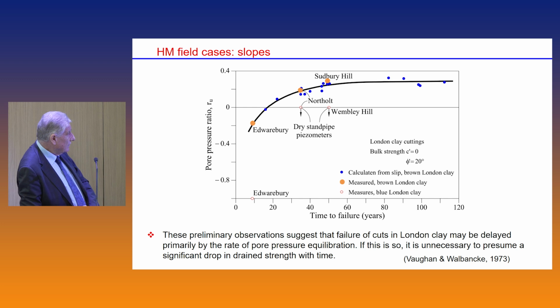In fact, when you put together those observations with the back analyzed pore pressures from the failures, they came out on a very nice single curve. That's taken from the paper. These preliminary observations, they are not preliminary anymore because they've been confirmed, suggest that failure of cuts in London clay may be delayed primarily by the rate of pore pressure equilibration. If this is so, and that's the important statement, it's unnecessary to presume a significant drop in drained strength with time.